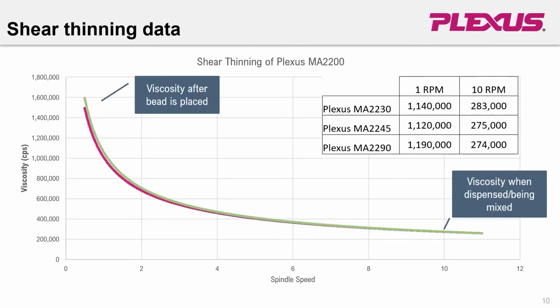A question that we get asked sometimes is, how come on your tech data sheet you say between 200 to 300 or so thousand centipoise viscosity? Your competitors are over 1 million, yet you can dispense and lay down just as thick of beads and stack them up as well. Well, that's because the Plexus materials have very nice shear thinning properties. So when they're getting mixed and while they're getting pumped, the viscosity goes down. Once you place it and it stops moving, the viscosity builds rapidly to over 1 million centipoise. This phenomenon allows for better mixing, easier pumping, yet a great gap filling capability.